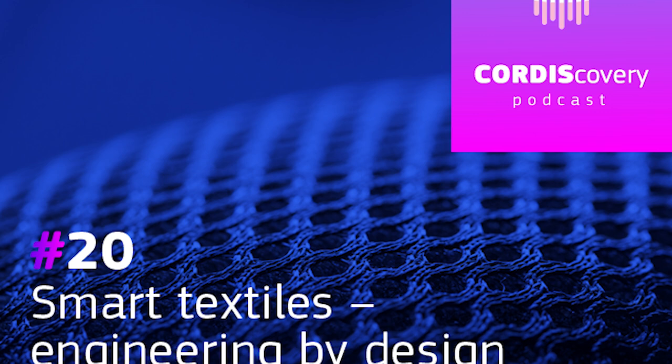And that was quite a challenge because, again, I mentioned that to produce this circuitry, you need a certain gap between the lines of the circuit. And so, as I said, we need to make sure that catalyst didn't spread. But yeah, that allowed us to get our conductivity and connectivity on the insole, and also we were able to print copper to where the pressure sensors would connect into the insole.